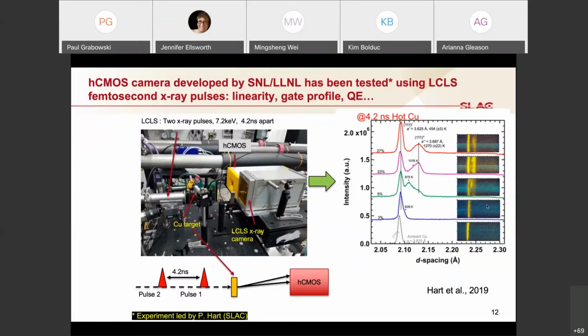So here on the right-hand side is a graphic from Philip's paper in 2019, basically showing X-ray heating of copper, and as we understand it, the first pulse is actually heating the copper, and the second pulse then probes that copper, and so we end up getting a doublet, peaks shifting in D-spacing, and that graphic is shown there.